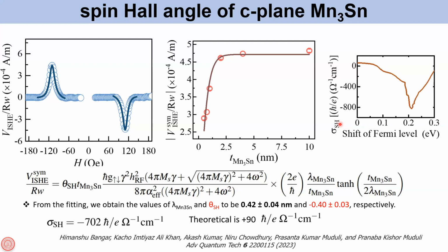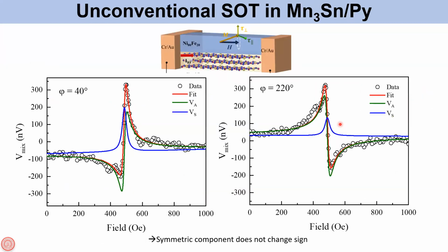So then we looked at spin orbit torque, and for that we need to make devices and then pass RF current. And these are some examples of STFMR measurements on the same sample. You see that as you reverse the direction of the field, the symmetric component shown in blue does not reverse its sign. So this is an indication that there is some unconventional spin orbit torque present in the sample.